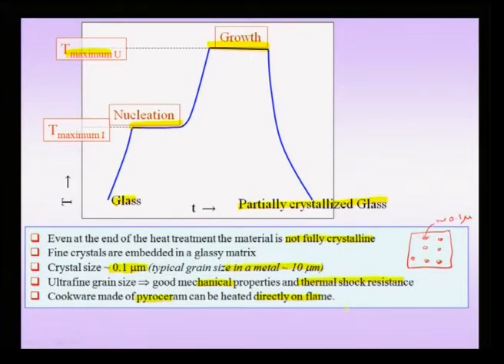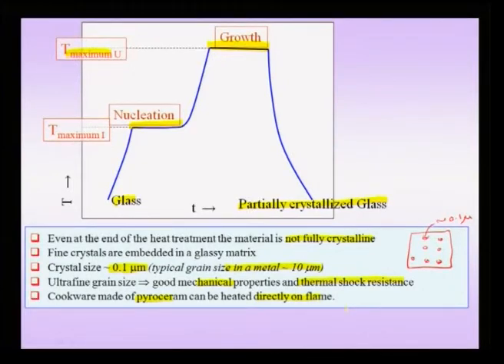To summarize: we have two distinct levels of control over properties — at the crystal structure level and at the microstructure level. Microstructure is defined as the combination of phases, defects, residual stress state, and their distributions. We can do microstructure engineering to directly control properties — as seen with hardness and tensile strength in steels, strength of aluminium alloys by precipitation hardening, and here where a starting glass is engineered by producing a fine distribution of crystallites to give both easy formability and good resistance to spalling.